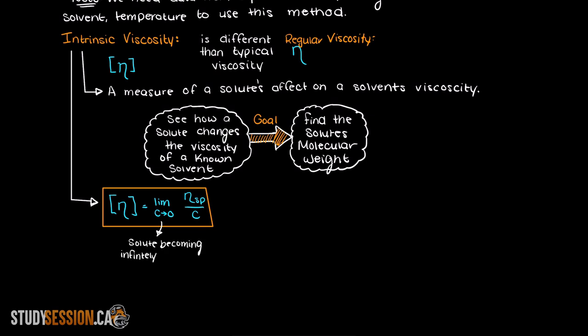In terms of concentration, think of the solute in the solvent solution as becoming infinitely dilute. However, it is not really possible to add an infinitesimally small amount of solute to our solvent. So what do we do? Well, we need to find another way of determining this. We find this through plotting the reduced viscosity by varying concentrations of our solute in our solvent, and the intrinsic viscosity will be the y-intercept of this.